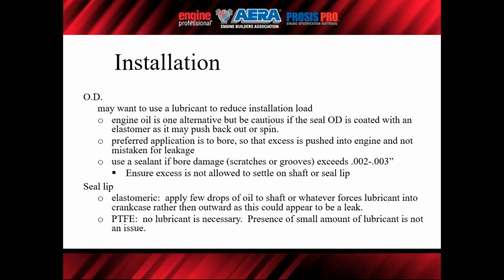PTFE, Teflon lay-down lip seals: lubricant is not necessary. We are in the business of building engines, so a small bit of lube from having oil on your fingers and whatnot is not the end of the world. But you don't purposely put oil there, or it will cause the seal to not condition itself to the shaft.